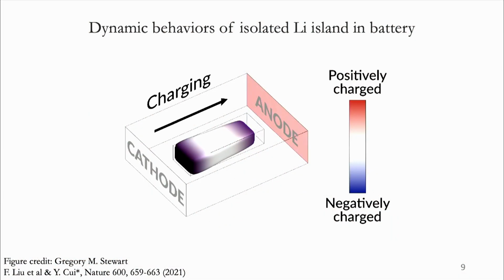So if we put those phenomena together, if we use the same current density during charging and discharging, this lithium filament will move back and forth between two electrodes until it's completely consumed. But our opportunity also lies in this phenomenon, because the rate of this movement is dependent on the current density. So what we're trying to see is whether we can somehow manipulate the behavior of the filament to help it move toward the anode side to reestablish the electrical connection, to recover this lost capacity.